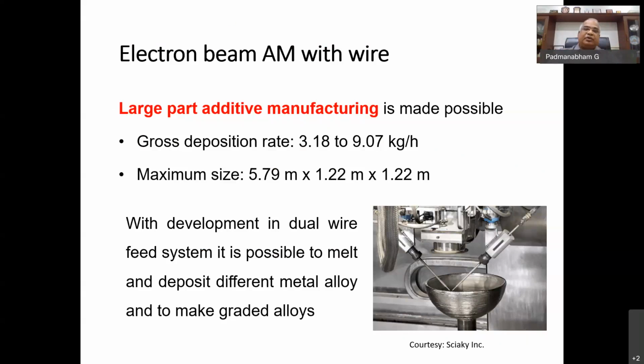Instead of using powder, you use wires. Use the electron beam to melt the wires, and deposition. You can see a machine from Sciaky. A substantial increase in the deposition rates is possible now using such machines. And then the size of the components also, like 6 meters by 1.2 by 1.2 meters, using 2 feedstocks, 2-wire feed systems, and deposit a large amount of material. So this is a trend now. Large components can be manufactured at high deposition rates.